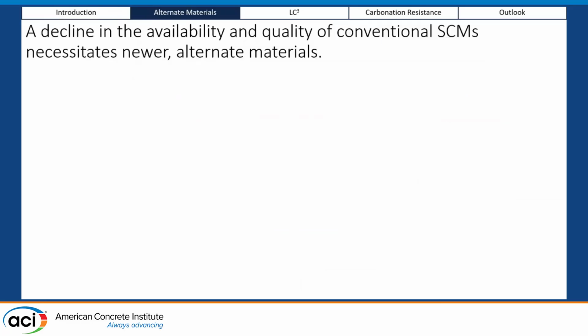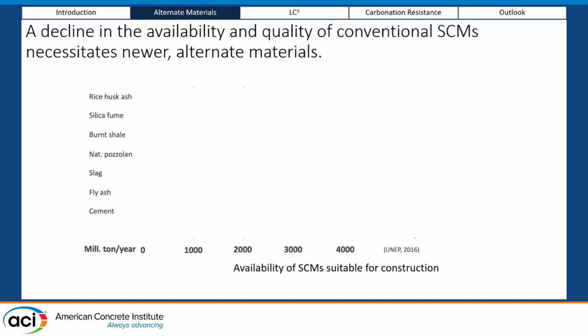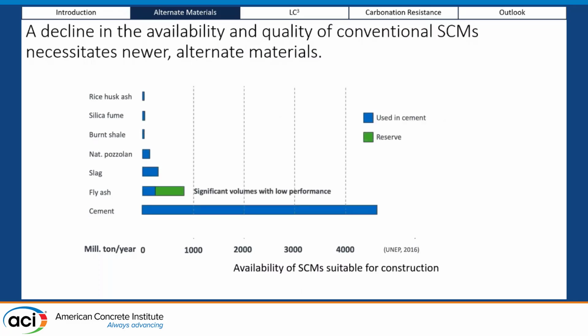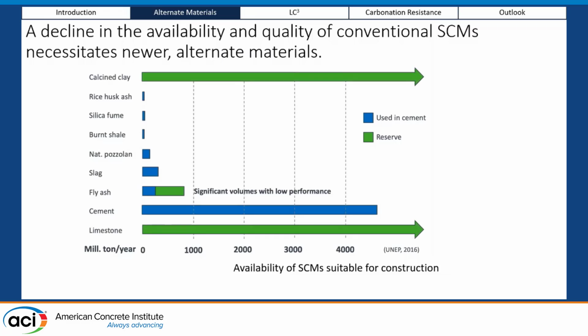A decline in the availability of conventional SCMs, especially fly ash and slag, necessitates that we move towards different or low-clinker supplementary cementitious materials. In this case, we have calcined clay and limestone, which are abundant in regions where construction demand is rising, especially in regions in Asia and Africa. So that is why LC3 has been a very attractive alternative to OPC, with similar, if not better, performance from a mechanical and durability perspective.